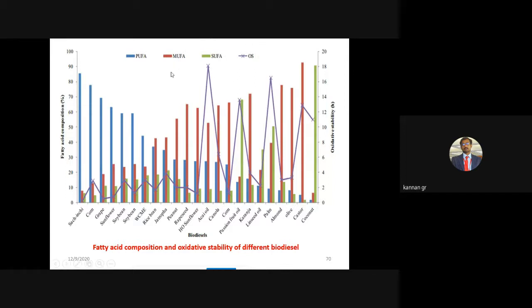In this case, a higher weight percentage of MUFA and SFA will provide maximum oxidation stability. But when we remove the polyunsaturated fatty acids, we can have great control over the oxidation stability. So the limit for biodiesel is about 3 hours, and for the biodiesel blend 6 hours, but here the oxidation stability is given in terms of hours. The maximum oxidation stability is for acai oil, then passion fruit oil, then palm oil, almost 16 to 17 hours.